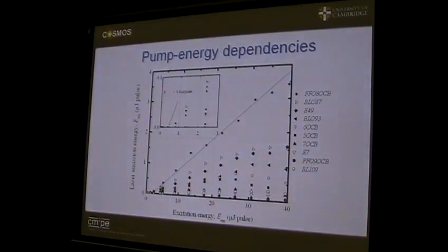And if you look at, under the same conditions, the same reduced temperature below the phase transition, there is a telling number in here. If you look at this curve here, that is the lasing from the bimesogen. Okay, and if you look in the literature, there are lots of little laser papers down here based around E7. It's about a factor of 10 lower in slope efficiency. So your threshold, and that's magnified threshold in there, is around, in this case, 0.4 microjoules per pulse. It's not unusual to get down to about 18 nanojoules now.